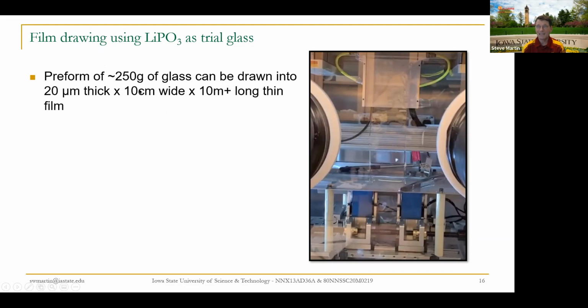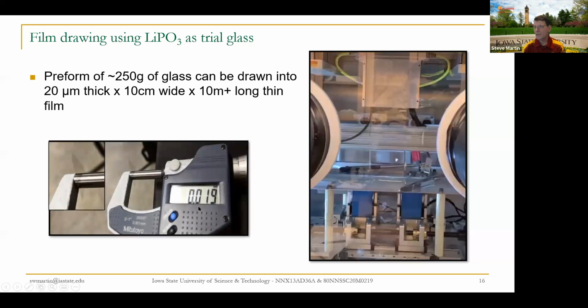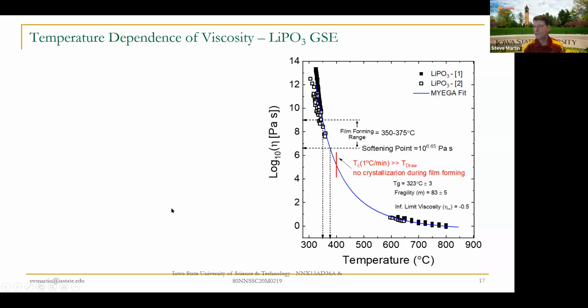We don't make the kilogram preforms yet. That's just a lot of glass. We don't need that much glass. We use about 250 grams or so. And here's just a micrometer. We break off a little piece of that. We're pulling about 19 microns to 20 microns, so we can pull that.